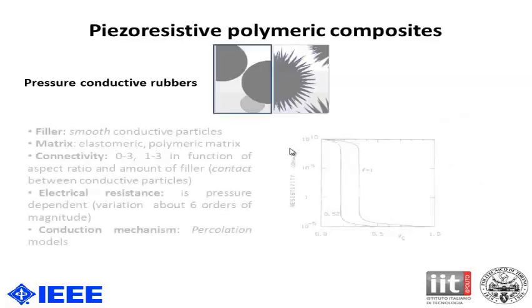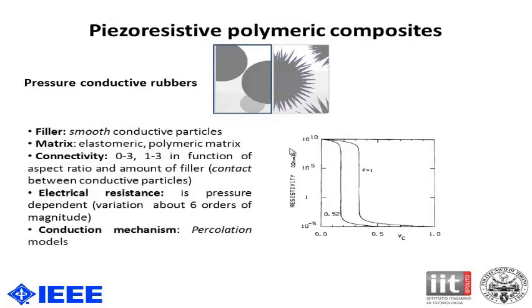The piezoresistive polymeric composites can mainly be divided into two great categories. The first are pressure conductive rubbers that use a smooth conductive particle inside the polymeric matrix, and the connectivity is of the type 0-3 or 1-3, where the first number is about the connectivity between the particles: 0 means that the particles are completely not in contact between them, and 1 means that they are in very small contact.